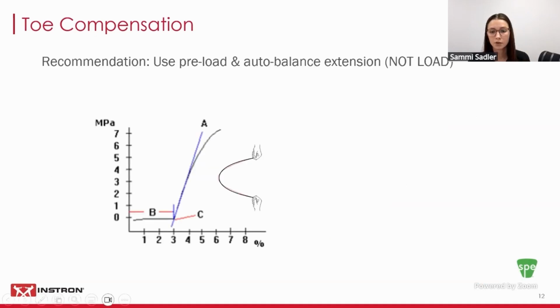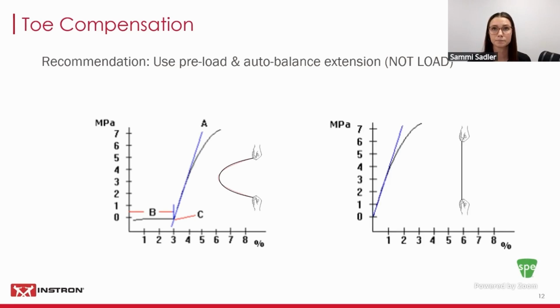The process to remove the slack from the material before the test begins is called a preload. This is where the crosshead will move to a certain distance to achieve a force value, such as 2 newtons, to remove the slack from the material so it becomes nice and taut. It's important to note that the distance that was traveled during this process is not the specimen straining. So therefore, we should auto balance the strain values after the preload value is met.